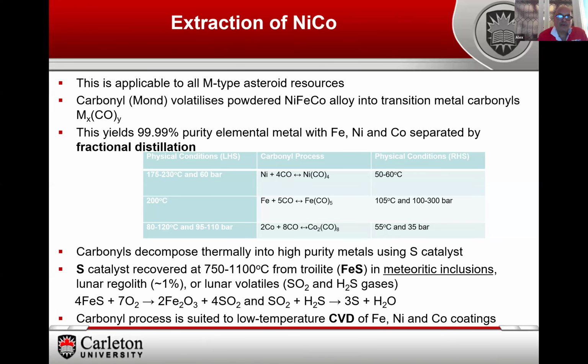So once we've extracted this nickel iron from the subsurface, we then need to separate it. In fact, there is a technique called the carbonyl process, which is extremely dangerous, by the way, because it basically converts metal into vapor, which potentially you could breathe, which would be disastrous. And once it's in vapor form, in the carbonyl form, we can fractionally distill it and then decompose and purify it back into its metal.